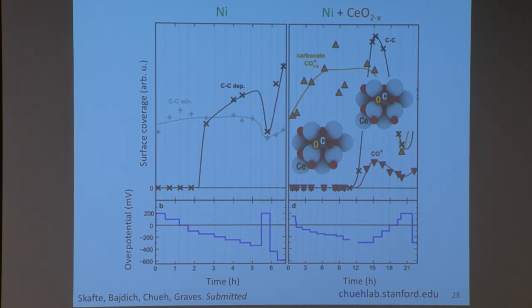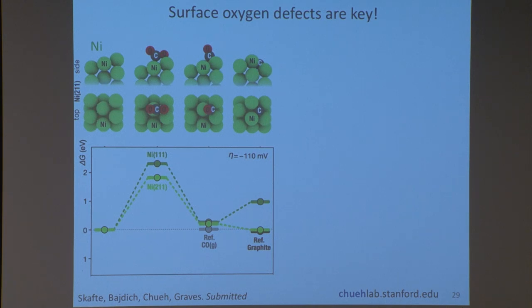And to rationalize the set of dynamics, so we're observing as CO2 is being dissociated into carbon monoxide and to carbon, we are using modeling to understand the reaction pathway to explain the set of data we have. So this is a plot showing you the sequential deoxygenation of the material. So you start with CO2, okay? You remove one oxygen, then you remove two oxygen. So here is basically CO2 gas. This is CO2 on the surface, CO on the surface, and then carbon on the surface.